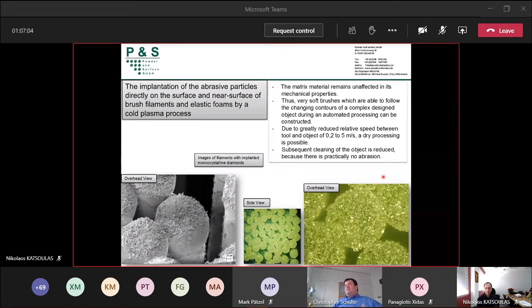The matrix material remains unaffected in its mechanical properties, which means that very soft brushes, which are able to follow the changing contours of a complex designed object during automated processing, can be constructed. So your brushes still remain smooth, so they are very gentle in the working process, and you can follow the whole structure. It doesn't matter if it's a complicated geometry or not. So you have a total abrasive functionality with a very smooth base substrate.